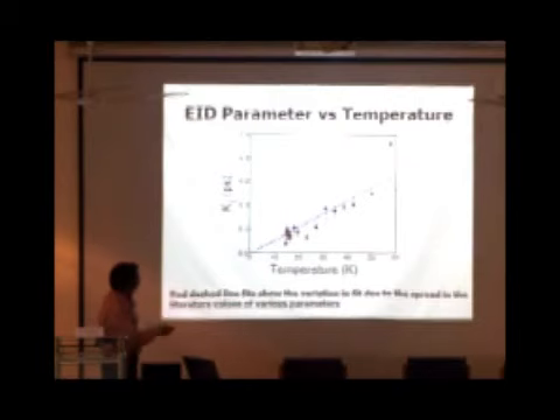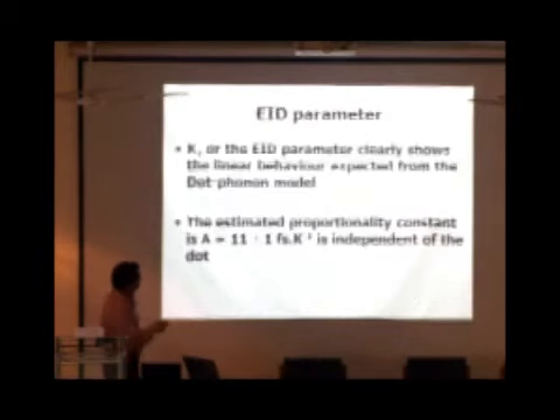So this is K2 as a function of temperature. As expected, it's linear, and the variation in the literature values gives the variation in the fit parameters. From this we estimate that K2 is linear in temperature as expected for acoustic phonon mediated damping, and the A parameter is about 11 femtoseconds per Kelvin.